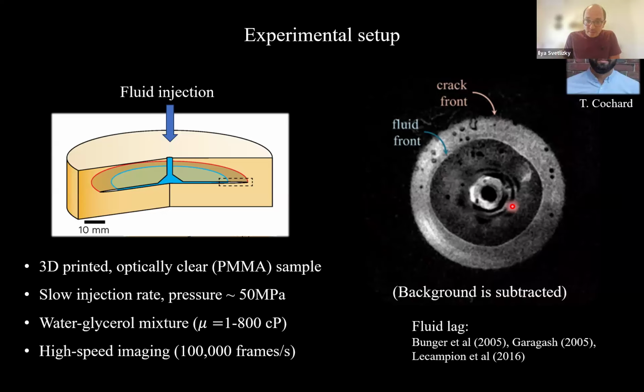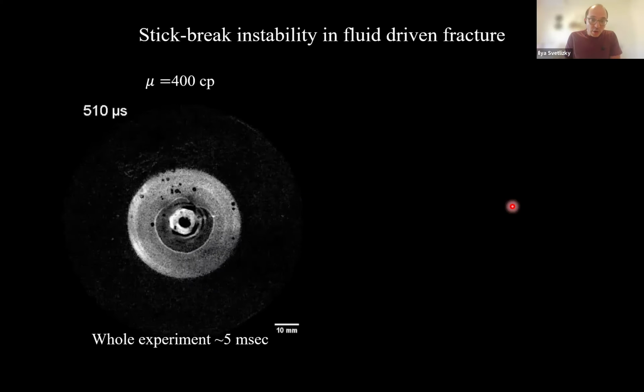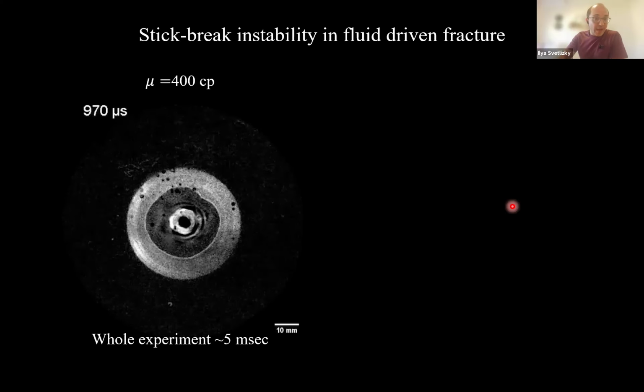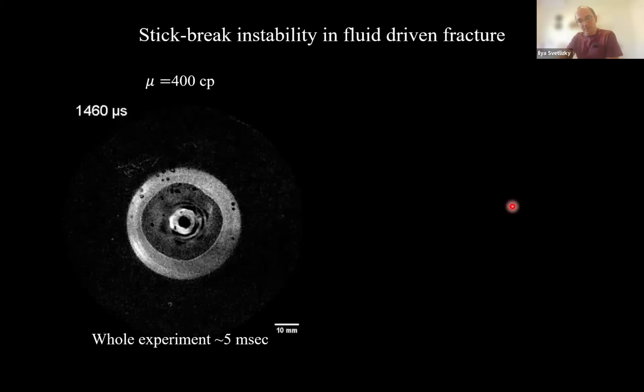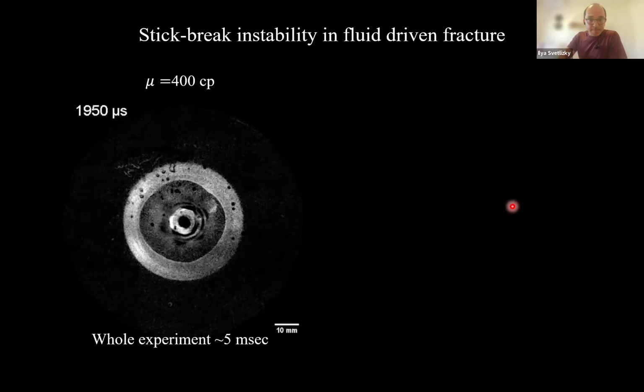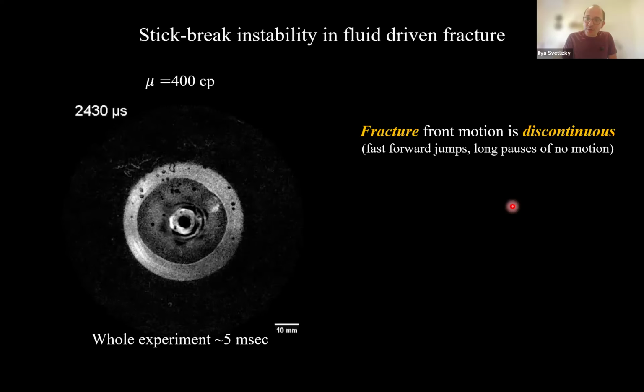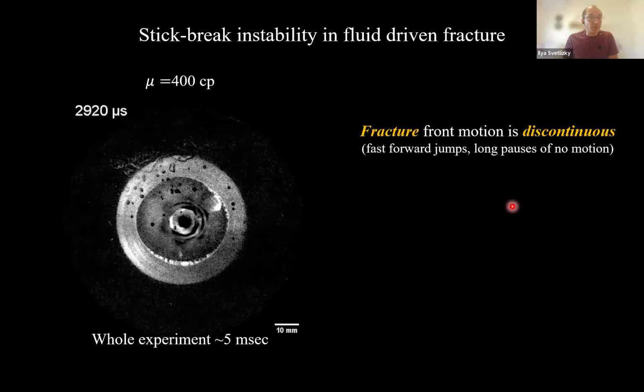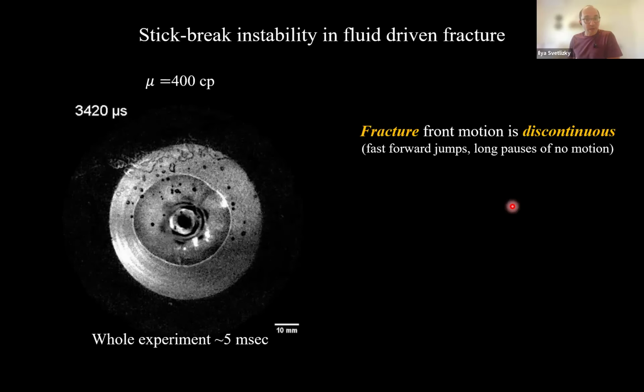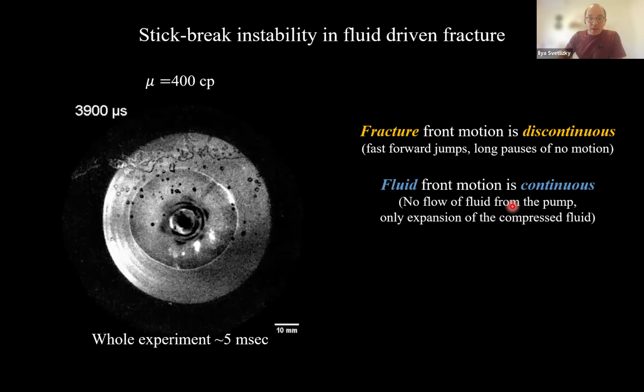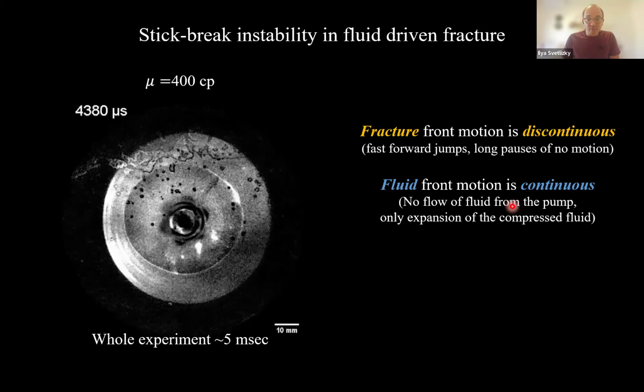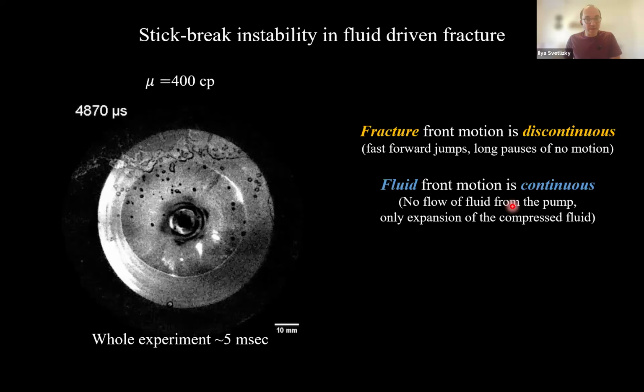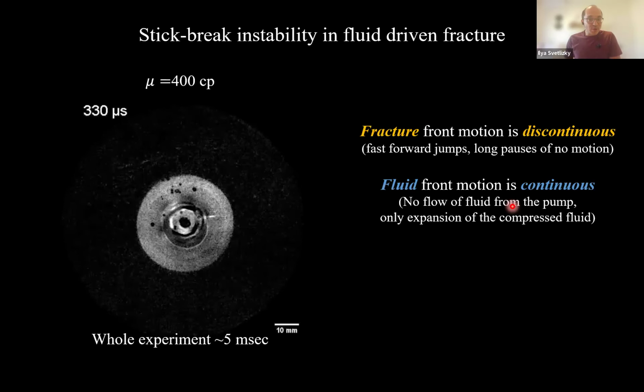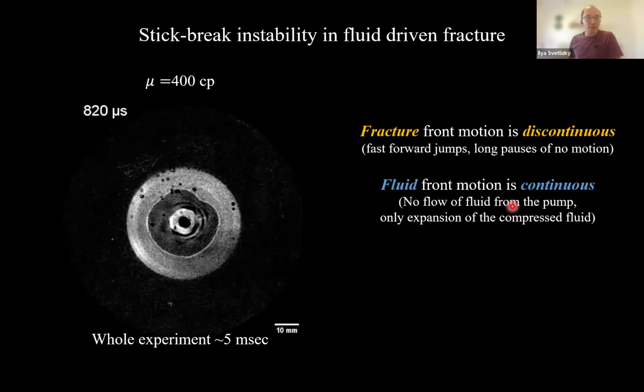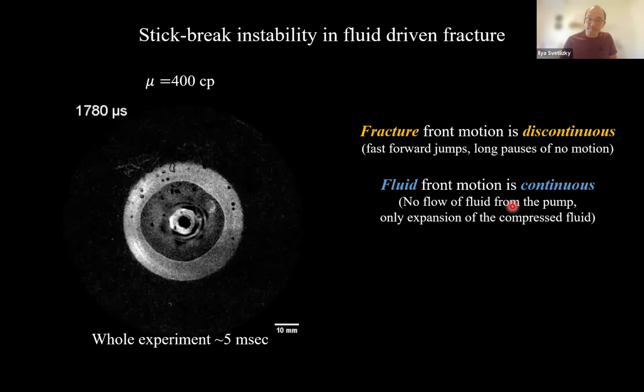So this is an example of an expanding crack. The crack runs, the fluid lags behind. I hope you see the movie. And the first thing that I want you to note is the fracture front is discontinuous. It jumps and then it stops. The pauses are very, very long. The second thing is the fluid front is actually very continuous. It expands, and importantly, the injection rate is really slow. So whatever you see now only happens due to the expansion of the compressed fluid.